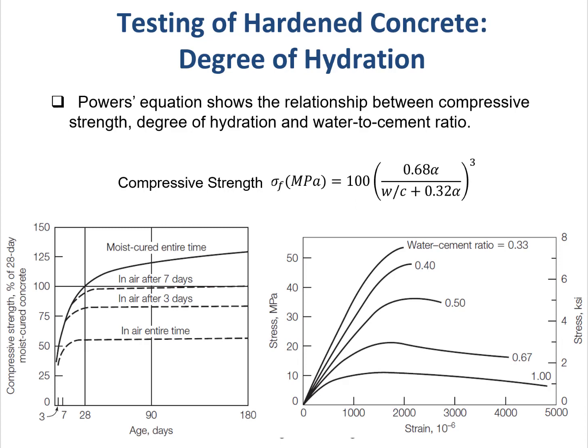So finally, let's talk about the relationship between compressive strength, degree of hydration, and water to cement ratio. From this figure, we can see that as water to cement ratio increases, the compressive strength decreases. And the compressive strength also depends on the curing time. From this figure, you can see the compressive strength actually increases with longer curing time. This is because curing allows continued hydration and consequently continued gain in concrete strength. In fact, once curing stops, the concrete will dry out and the strength gain will stop.